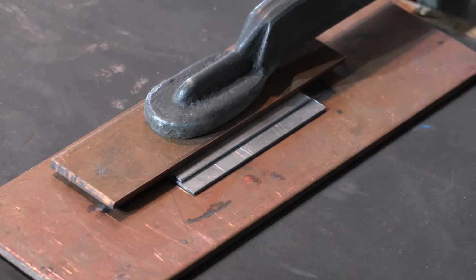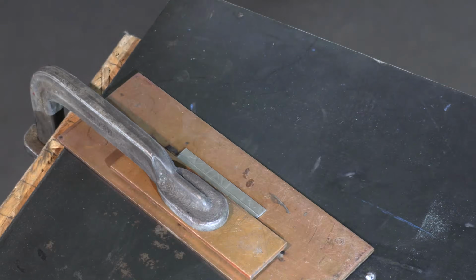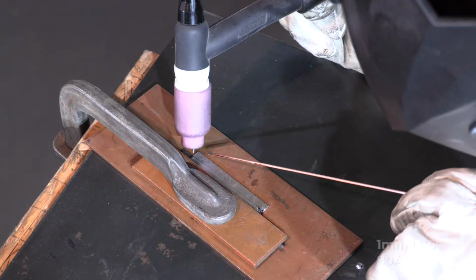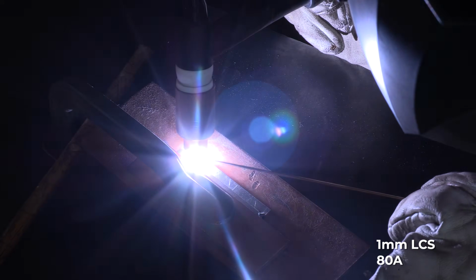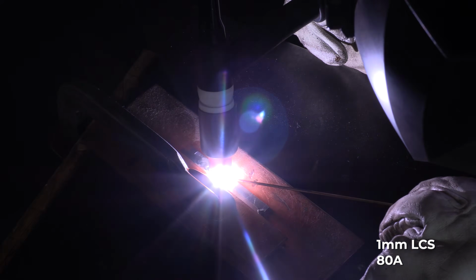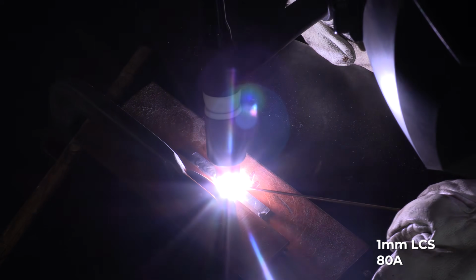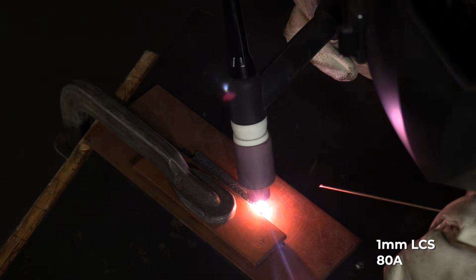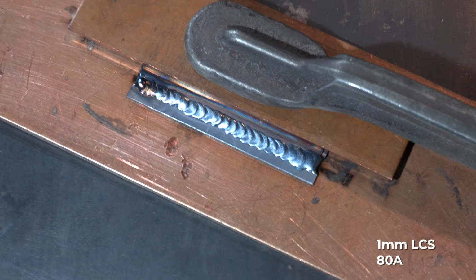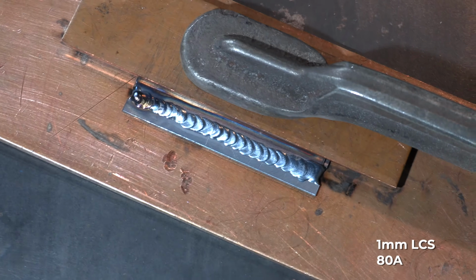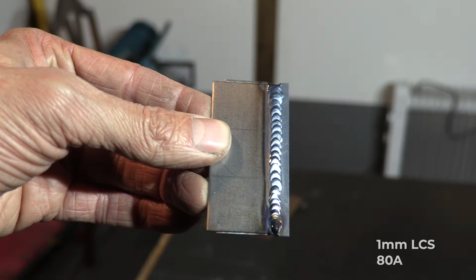Now let's add an extra strip along the top. So we have some copper backing the base metal as before, but also a chill laid on the top sheet. The amperage is exactly the same. I haven't changed a thing. Look at the difference. The amps are much closer to where they need to be. The bead doesn't look overcooked or burnt. Although it is a little bit inconsistent, it's still a big improvement. These 3 welds were all completed at 80 amps.